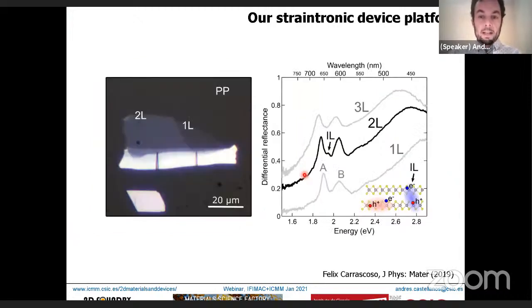Let's take a look at how this looks with thermal expansion of a polymer substrate. In this case we have a polypropylene substrate, and we have transferred a molybdenum disulfide flake - here a single layer and a bilayer. The way we monitor if we're transferring strain to our material, and if we're able to change its band structure with strain, is by making micro-reflectance spectroscopy measurements.